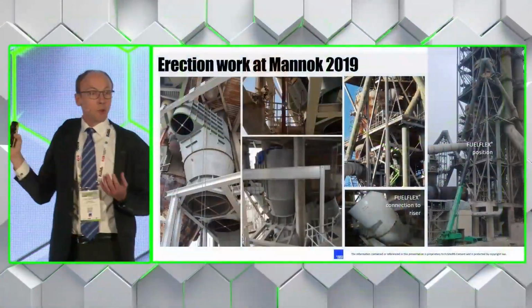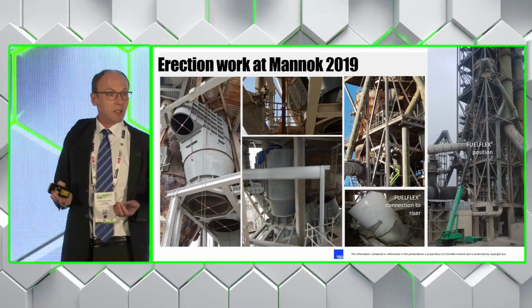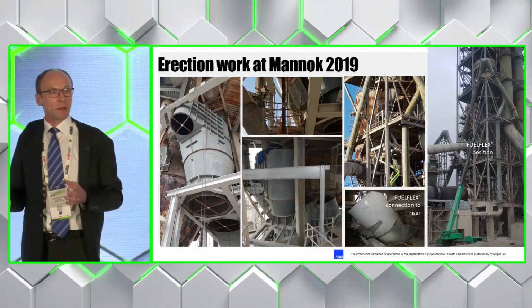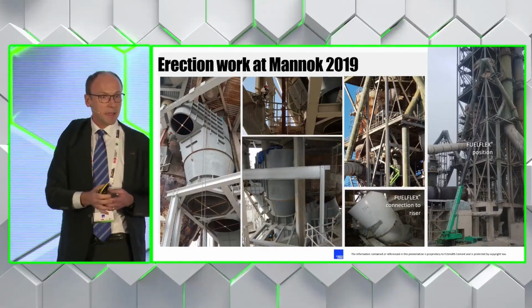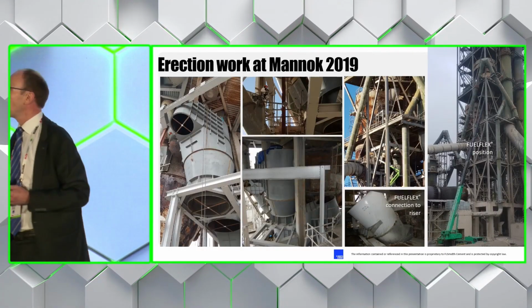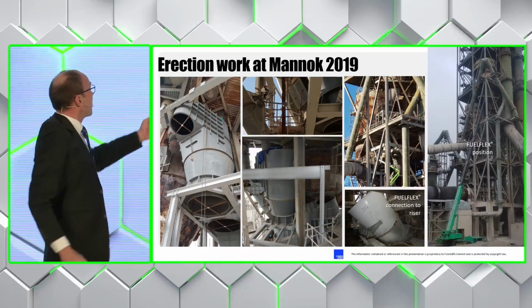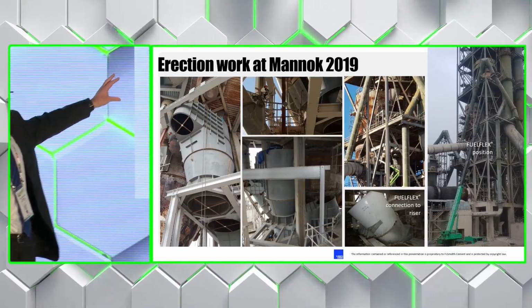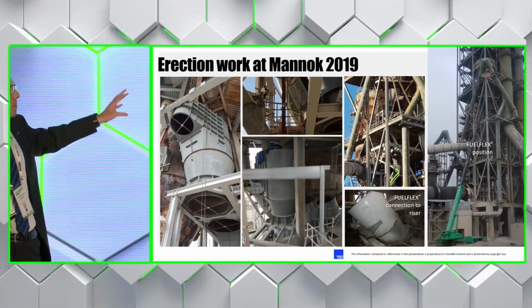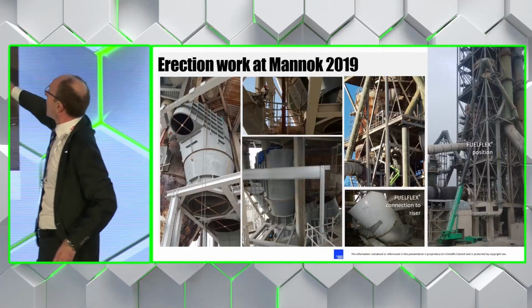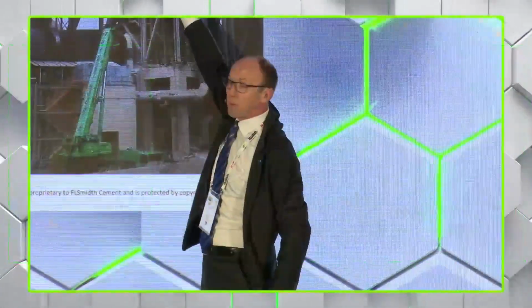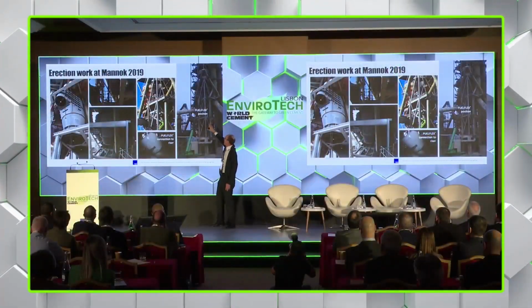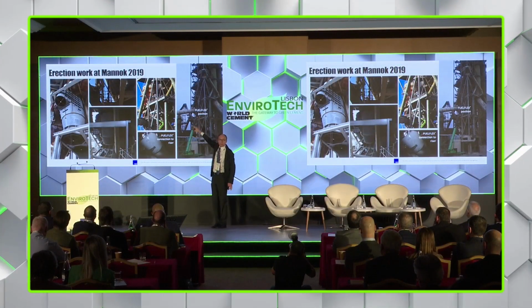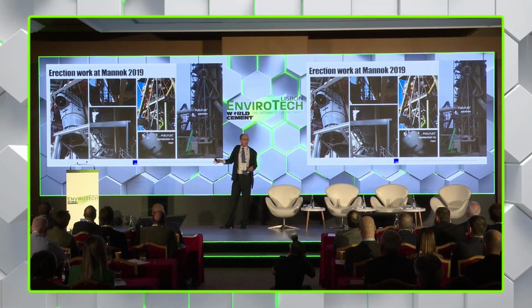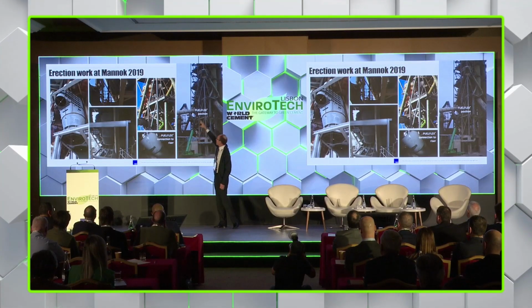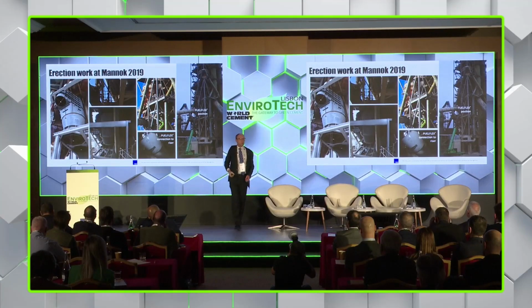We then, in 2019, did most of the installation work at Mannok. We actually started with the first parts in late 2018 and then concluded the work in 2020. What you'll see over here is the main pyrolyzer vessel, which fits nicely into the preheater. Then out here on the right, you actually see where the FUELFLEX Pyrolyzer fits into the preheater, and you can also see the space which is freed up in front of the kiln. This was where the alternative was to put in a big, costly calciner in front of the preheater.